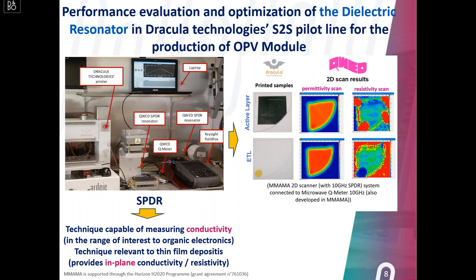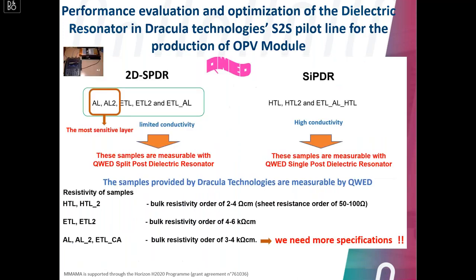This is something important for us. And also this technique can give us additional information. As we can see, for example, there are two ways to do the measurement. The first one is the two-dimensional SPDR, which in general is compatible with materials with limited conductivity, like for example the organic materials, like the active layer or the electron transporting layers.